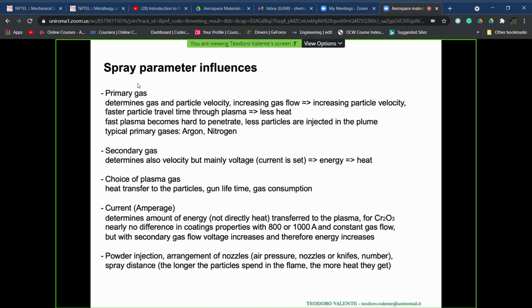and for primary as well as for secondary, we are going to identify plasma gases. Primary gas is very important for gas and particle velocity. If we increase the gas flow, we increase the particle velocity, so we do have faster particles, and these together lead to a reduced travel time through the plasma, that is, less heat is seen by the particles themselves. So it must be properly balanced in order to have the desired degree of melting of the particles which are